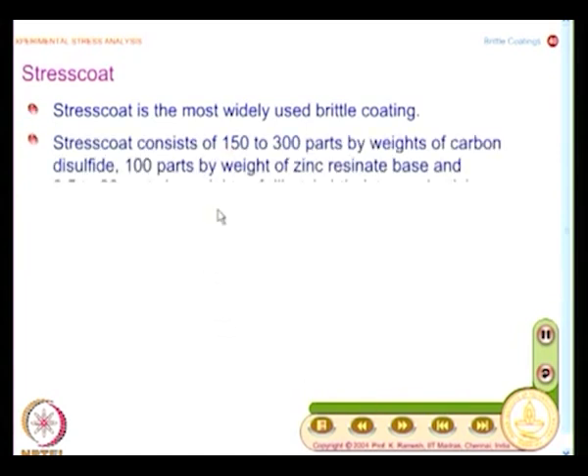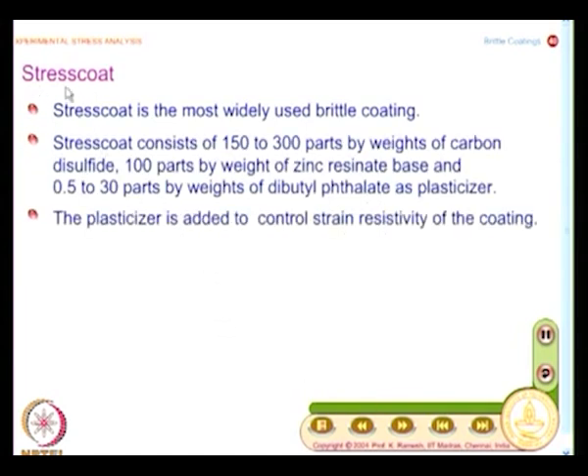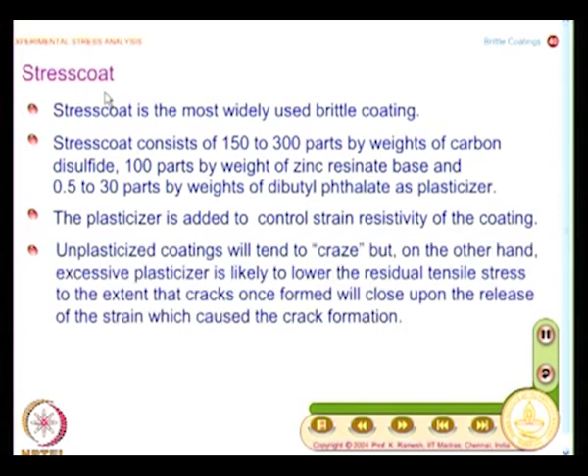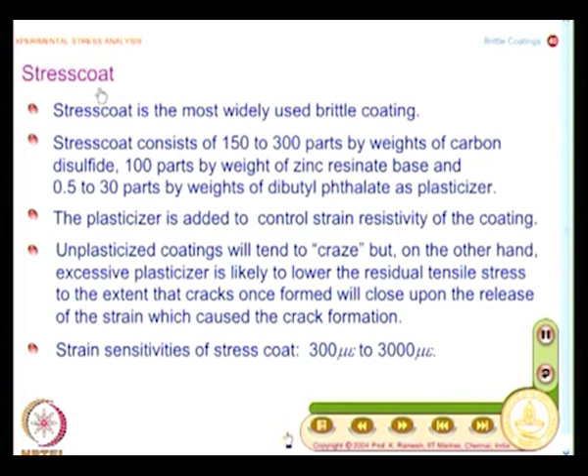What is the type of coating that is available now? You have what is known as a stress coat. I said that initial coatings were naturally formed coatings. Then we saw the first coating was a mixture of shellac and alcohol, and what you have widely now is called stress coat. The stress coat consists of 150 to 300 parts by weight of carbon disulfide, 100 parts by weight of zinc resinate base, and 0.5 to 30 parts by weight of dibutyl phthalate as plasticizer.